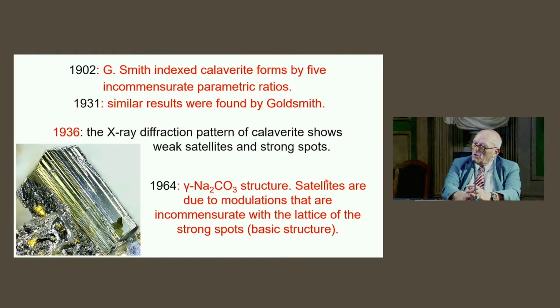Well, the problem was solved about 50 years later. In particular, at the beginning of the last century, Smith and Goldsmith measured calaverite, which has a lot of small faces, and the selected reflections were not originated by macles and so. Anyway, they were not able to index all the reflections based on a unique parametric ratio. They had to use more parametric ratios. Or if you like, they had to index some reflections with non-integer Miller indices.